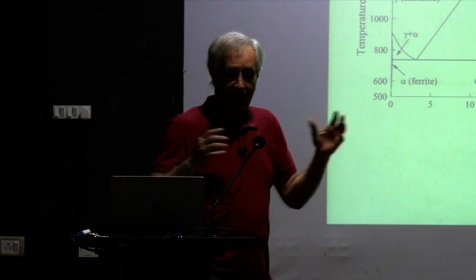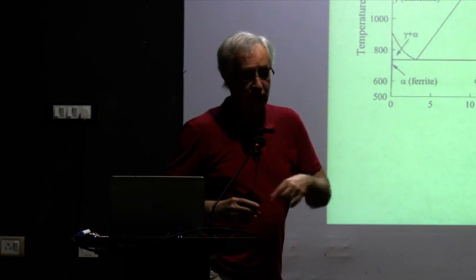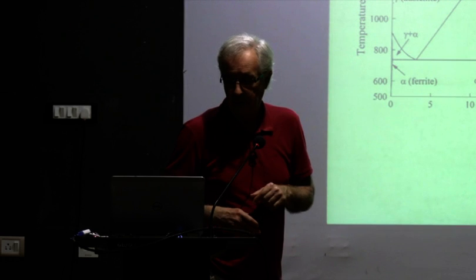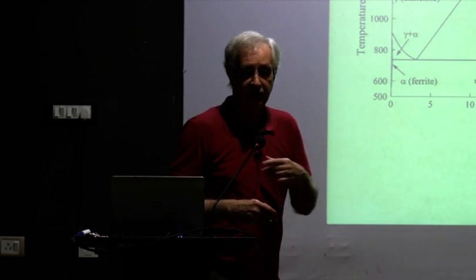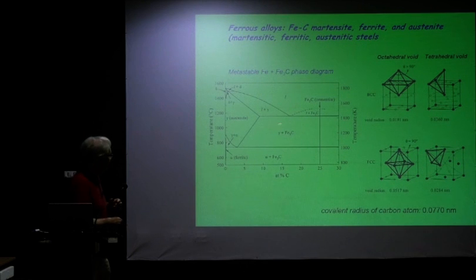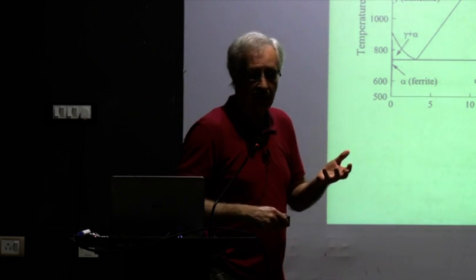And the reason why it can expand in all three directions is going to be more evident when I show you more about the expansion properties of these materials and the anti-Invar effect. So, if we are sitting at a very, very low carbon concentration, and we put carbon into the structure, it is possible to dissolve a certain amount of carbon into this void, so you get these things called the ferrites, okay?